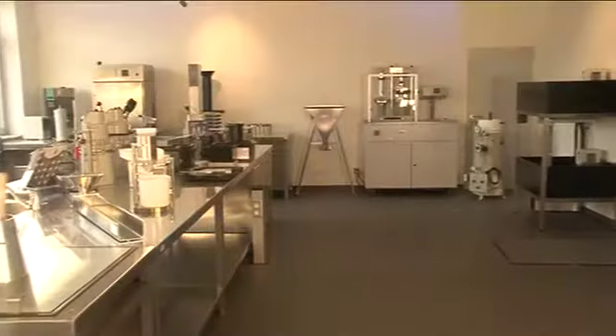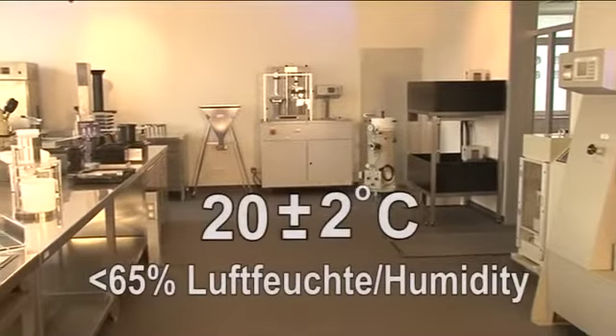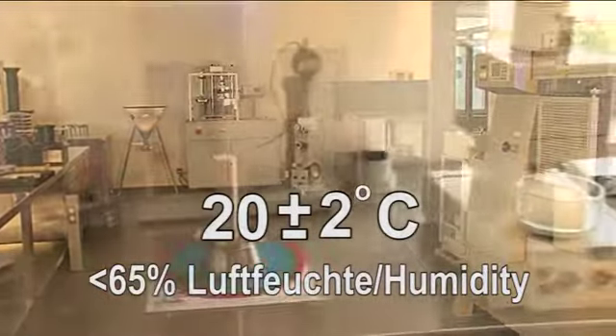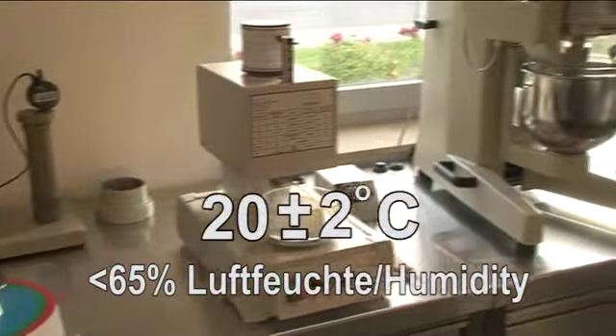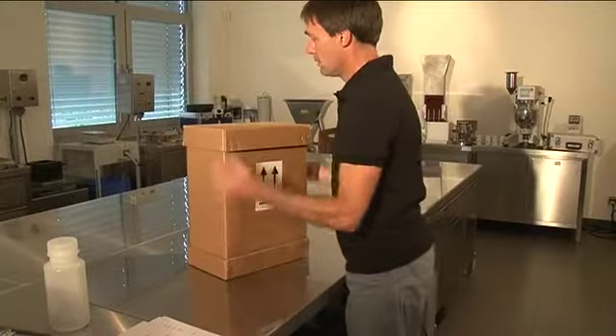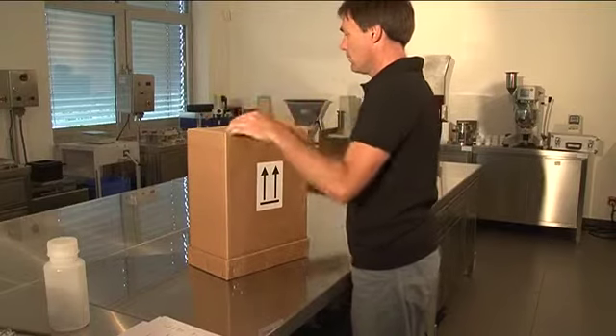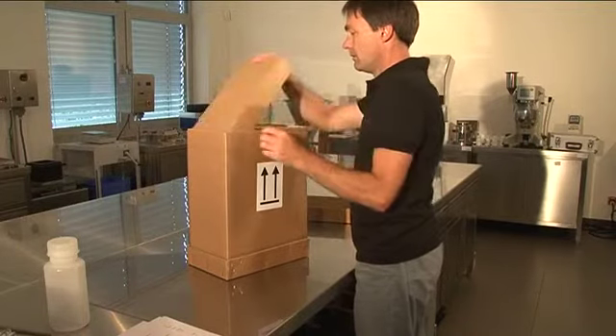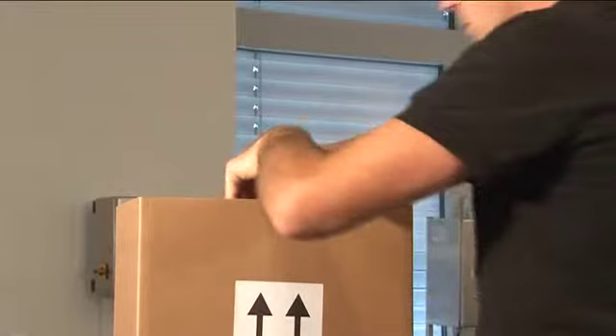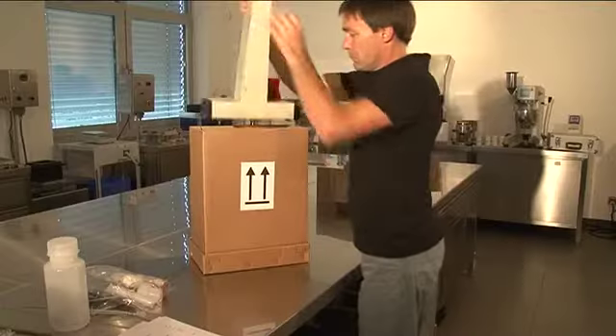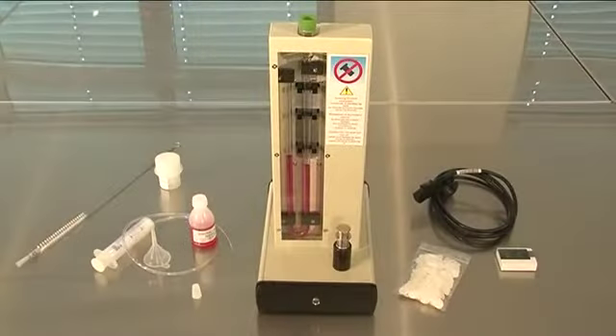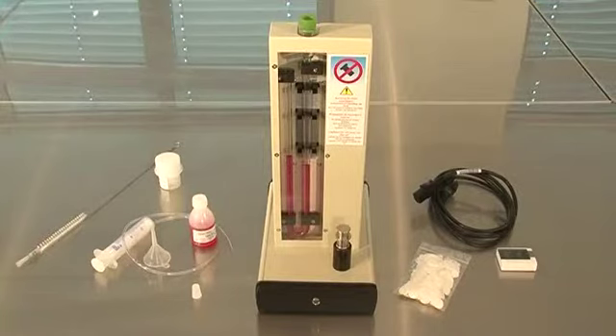The laboratory, testing equipment and test material must have a temperature of between 18 and 22 degrees Celsius, as well as a maximum relative humidity of 65%. Inspect the visible condition of a delivered consignment immediately. Any damage which occurred during transport or a shortfall in quantity must be logged without delay and submitted to us by fax or email. Use the delivery note to verify that the consignment is complete.